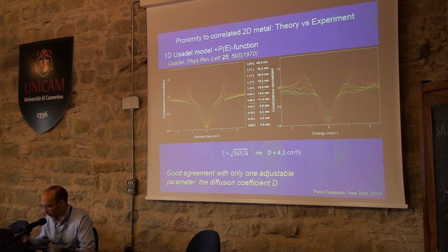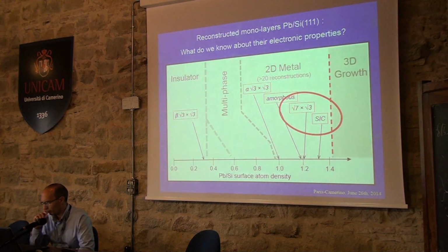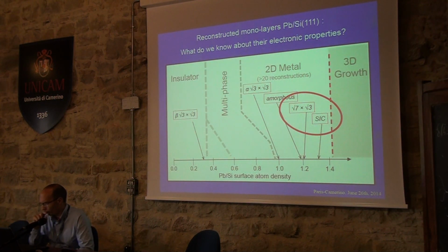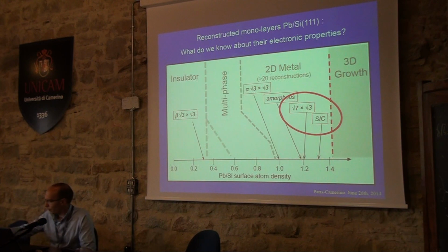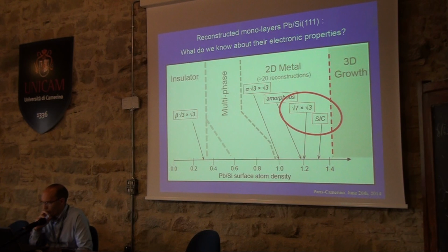So let us go to the next slide. And now I turn to the case of crystallized wetting layers. Amorphous wetting layers are not superconducting, but correlated metals. And probably the reason why they are not superconducting is related to the Coulombic interaction that does not allow the superconductivity to settle in. But if you crystallize this wetting layer, you can crystallize different structures, and the most famous are square root 7 by square root 3 and the so-called striped incommensurate structure.